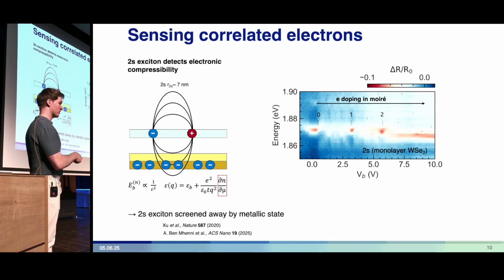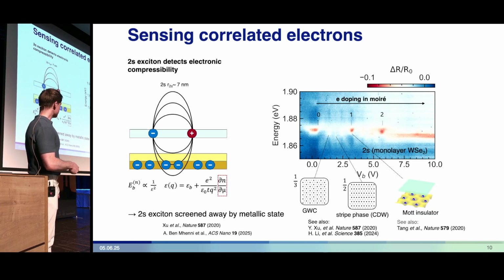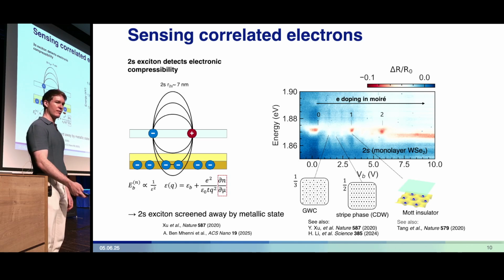Between these special points, the 2s exciton disappears. These points where the 2s exciton reemerges between 0 and 1 are actually generalized Wigner crystals that emerge from long-range interactions. The half-filling nu equals 1 charge per Moiré unit cell insulating state has been determined to be a Mott insulator by previous studies.